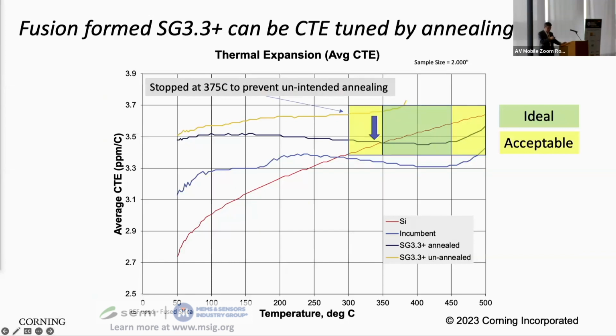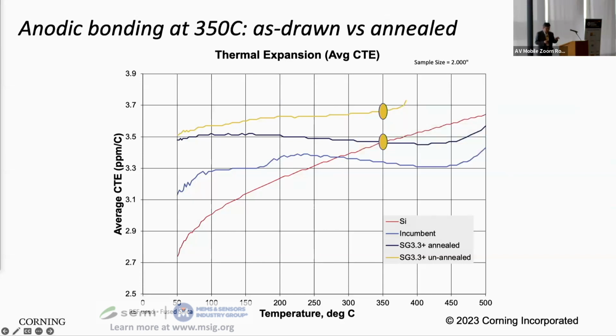So this is a little busy, but the red line or the orange line on top is the glass where we just draw it and without doing annealing. And you can see the CTE is a bit higher than silicon. So when you bond these two materials together, you have a bow. But if we anneal, the arrow is indicating after annealing, the CTE becomes the second highest line. I cannot tell the color here. And then the matching to silicon happens at 350, which is in the green zone, the ideal bonding temperature.